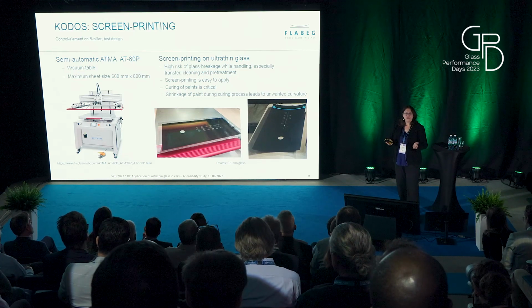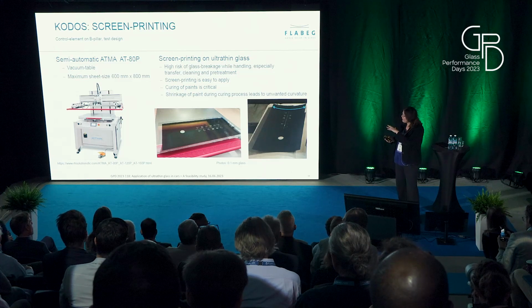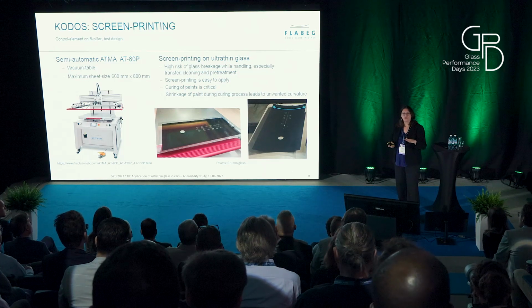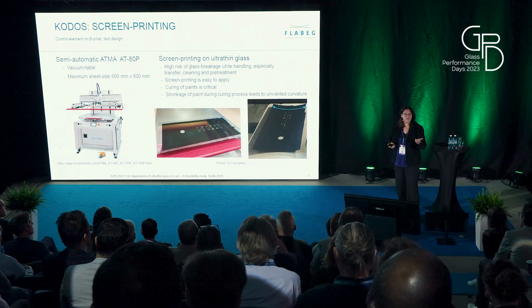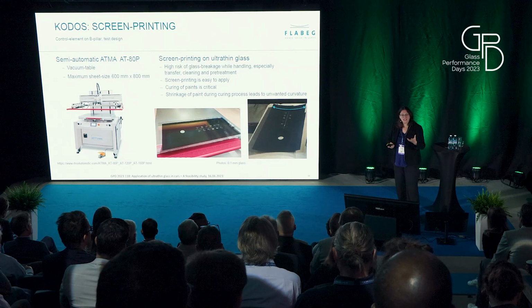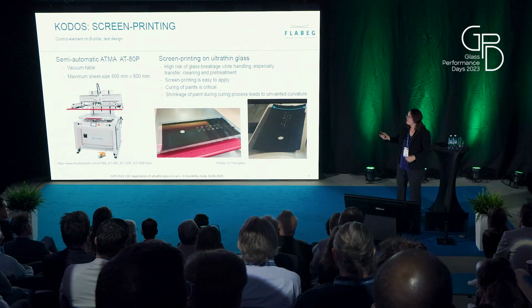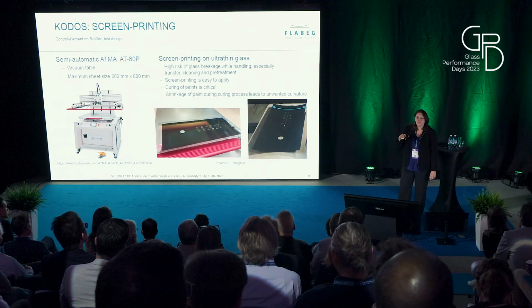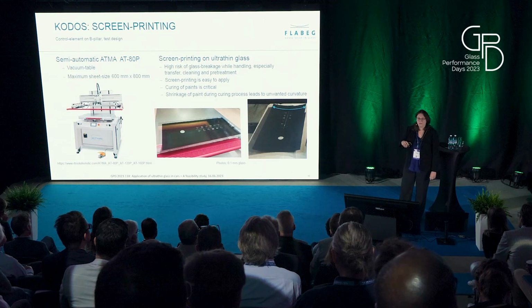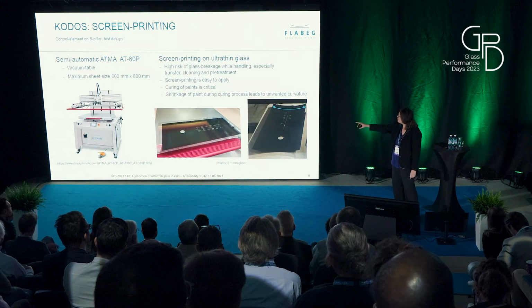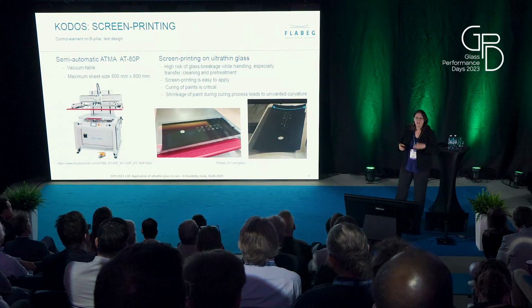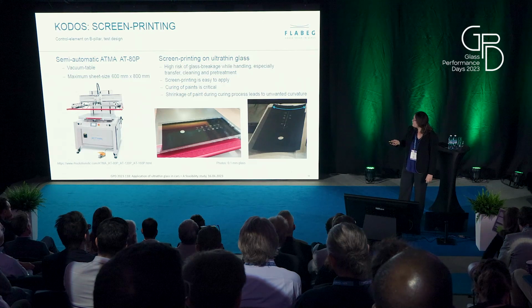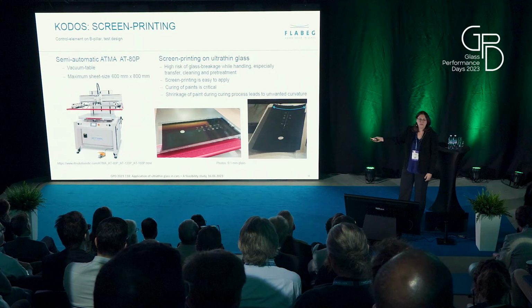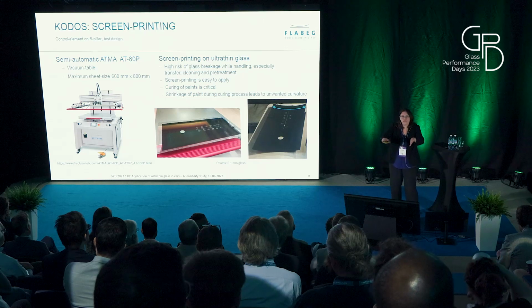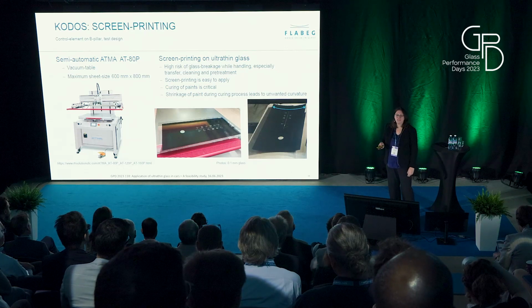Some people of you might know that this very thin glass is used in laboratories to identify an intrinsic stress in the films. Which is nice for analytics, is not helping us if you want to apply several layers and have to think of internal stress for all of these layers. So there has to be some work done to move on. For example, here we try to have some symbols for OLED illumination, and before curing it's completely flat. Printing is nice. After curing you had this curvature, and well, so the second layer is a problem.